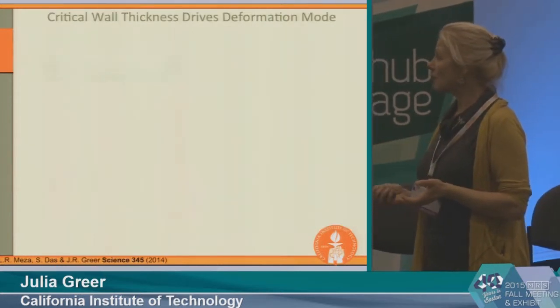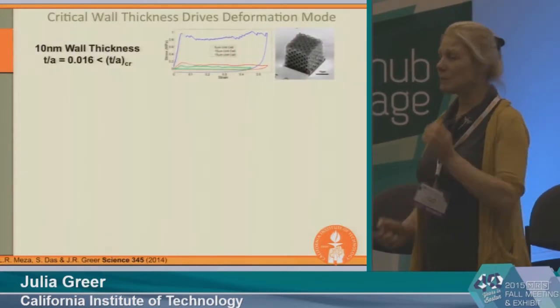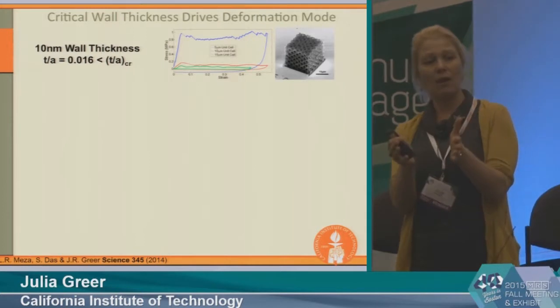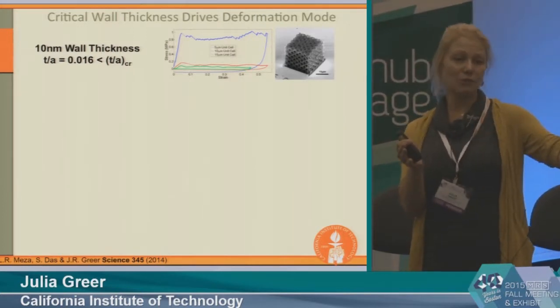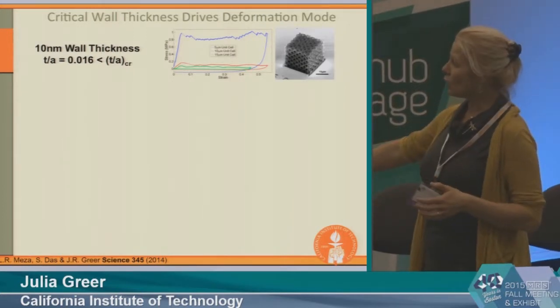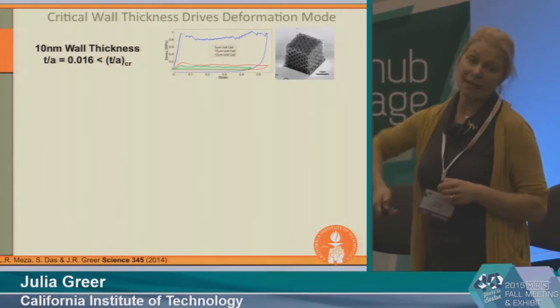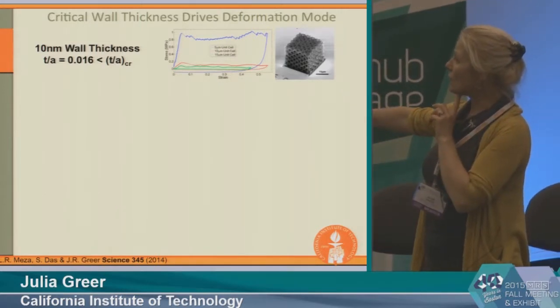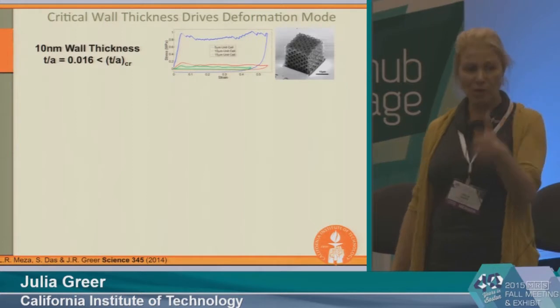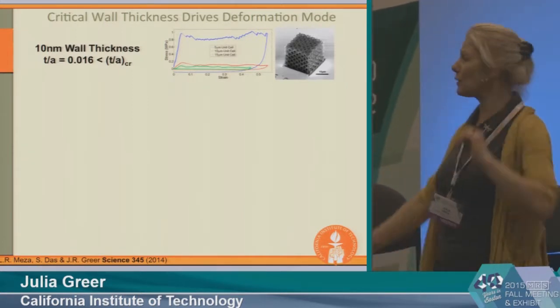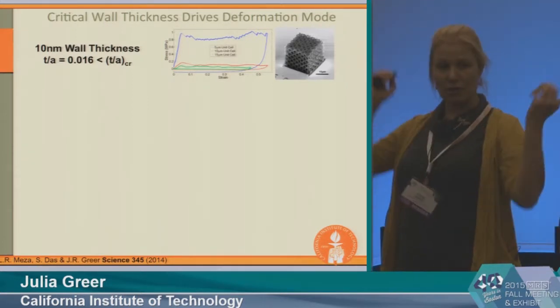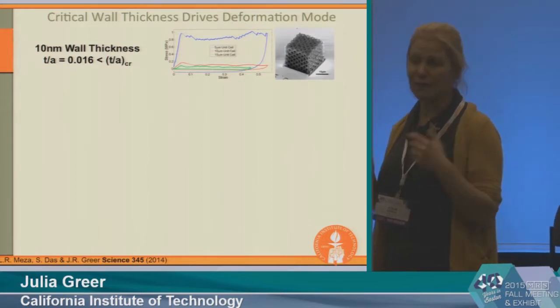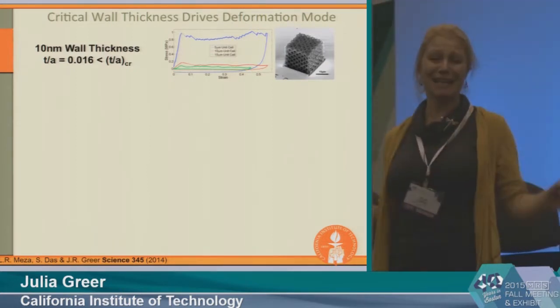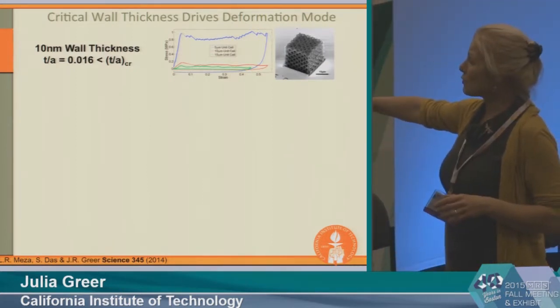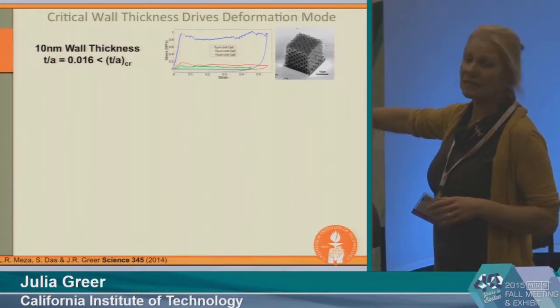Now the reason why this happens, it turns out, is because of this critical ratio between the wall thickness and the radius of the tube. And so when you look at something that's only 10 nanometers thick, it fully recovers even after you've compressed it by more than 50%, by more than its height. It fully recovers. This image is of a post-deformed nanolattice, and you wouldn't even be able to tell the difference. It looks exactly the same. You can see this is true for all different sorts of unit cells; every time it recovers.